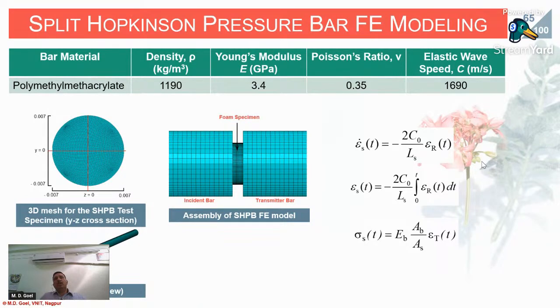Now, for example, I am a teacher working in some isolated place where this kind of facility is not there, but I have a computer with me, so I can simulate such tests directly. This is the FE modeling of the complete split Hopkinson pressure bar, where one can model the incident bar, the transmitter bar, and the sample. For example, here the foam sample was modeled by me. This is my PhD work, and I can completely model the bars, as shown on the down left side, and this is the sample size. The sample size is very small, only a 14 mm diameter sample.